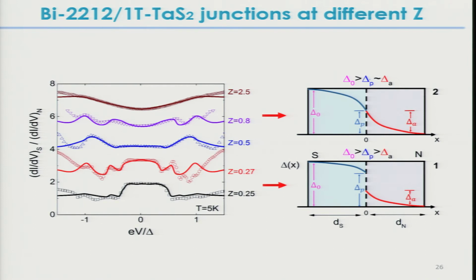So what we have here is a superconductor, and this is as a function of voltage. We've made 5 different junctions with different transparencies. These are low temperature data, 5 Kelvin. The lowest one, for those of you who do superconductivity, is a proximity effect. There's essentially, from the Bisco, a gap induced into this Mott insulating phase of tantalum disulfide.